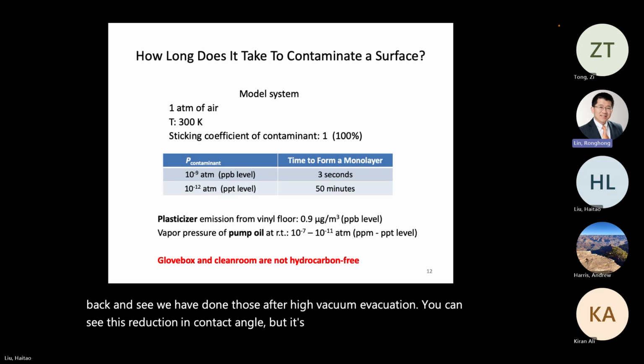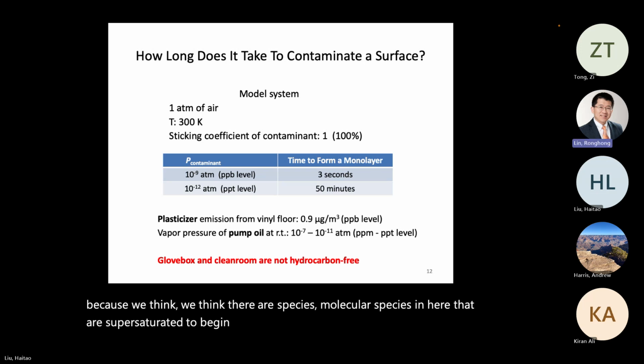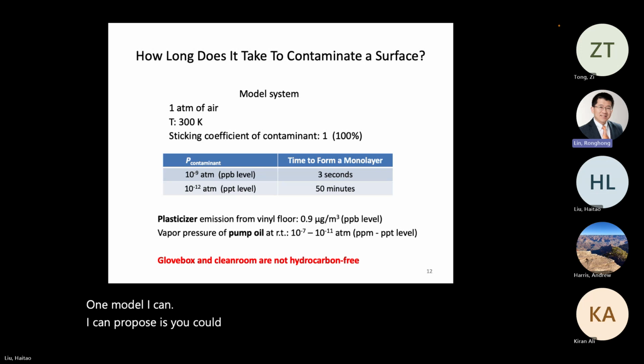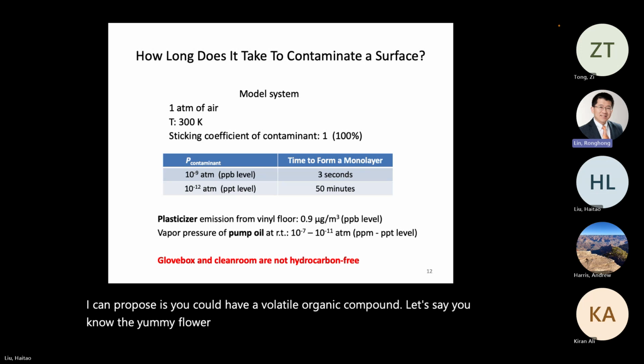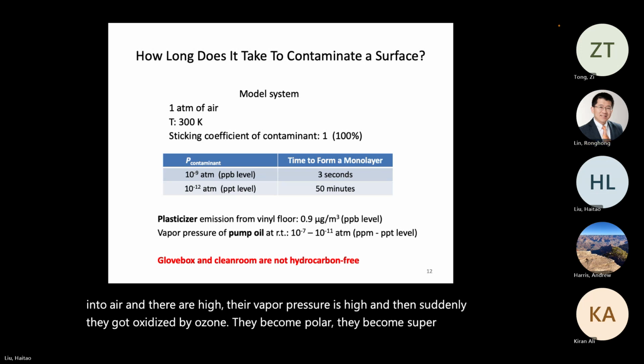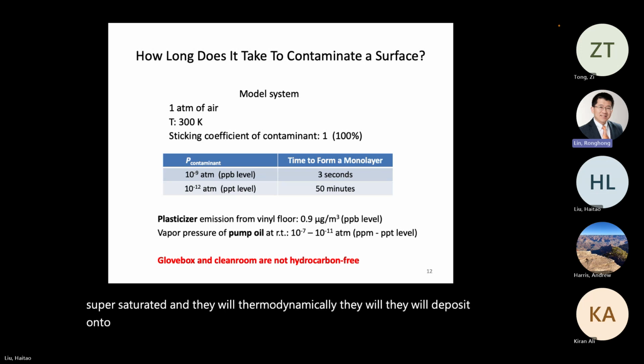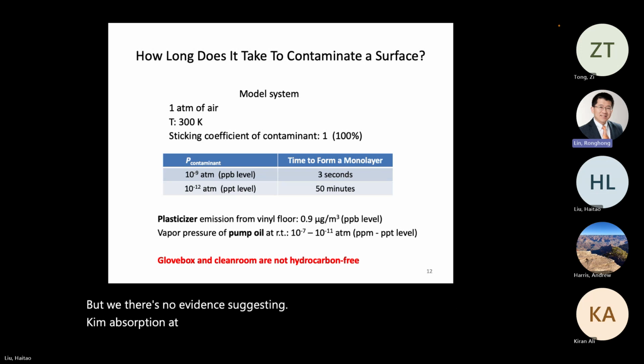contact angle, but it's never going to be complete, because we think there are molecular species in air that are supersaturated to begin with, to the point they will deposit onto any surface. It doesn't matter what their surface energy is. You may wonder why they would be supersaturated. One model I can propose is you could have a volatile organic compound, let's say the yummy flower smell or lunch smell, and then they come into air and their vapor pressure is high, and then suddenly they get oxidized by ozone, they become polar, they become supersaturated, and thermodynamically they will deposit onto anything as long as they can find a surface. They will deposit, and we cannot get rid of those materials. But there's no evidence suggesting chemisorption at this stage. The graphitic surface is chemically stable, and we don't expect chemisorption.